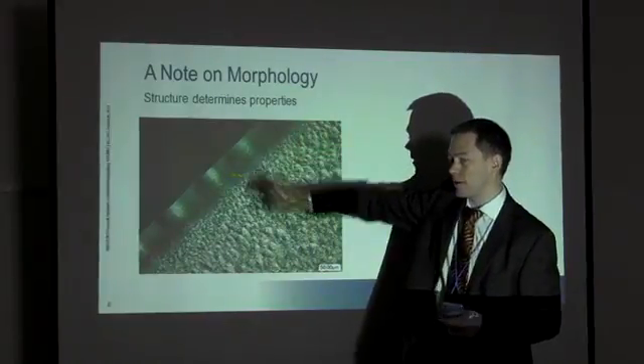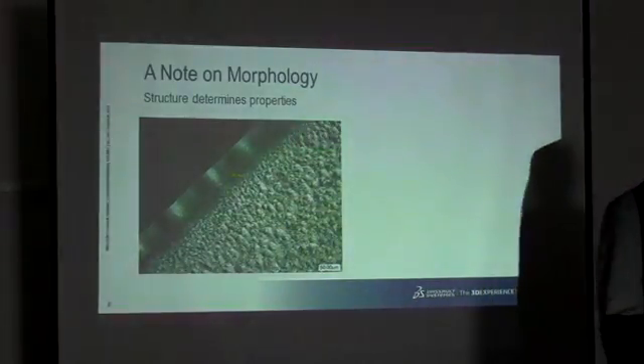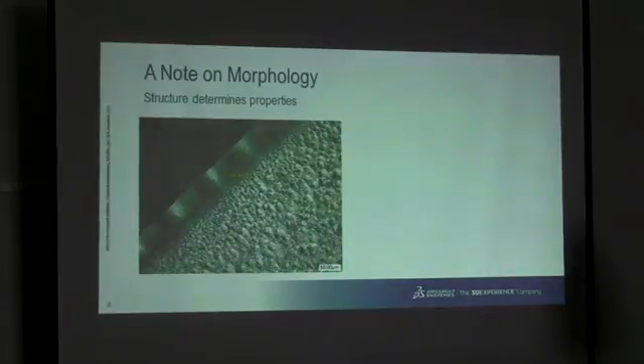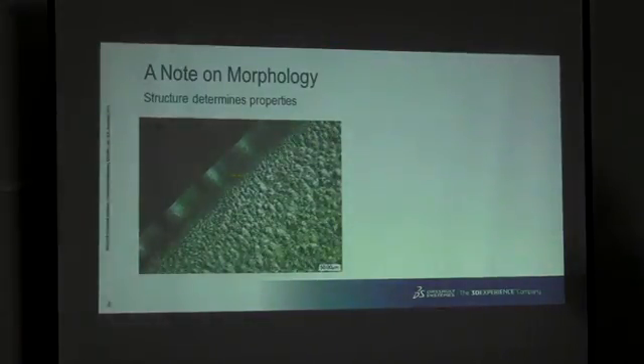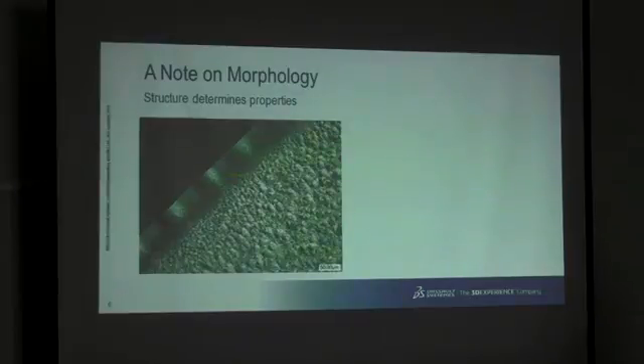This is the injection molding skin. That looks amorphous, and it's often classified as amorphous because it's transparent, which is not the case. It's highly oriented. When you shoot the molten plastic into the mold, it's got about the viscosity of water. Then it sticks instantly to the mold surfaces, boom, stretching all the molecules, and that gives you something which acts almost like a wrapping foil. Now, this wrapping foil is very important to keep in mind because it will prove one of the main indicators for why plastic parts fail the way they do.